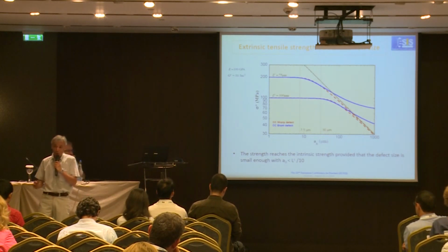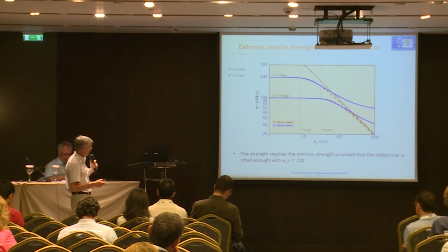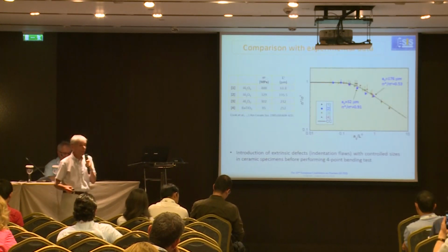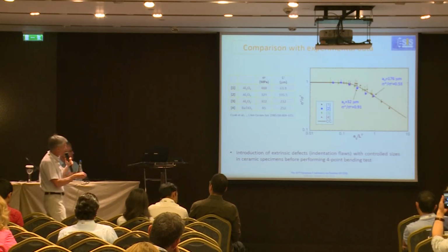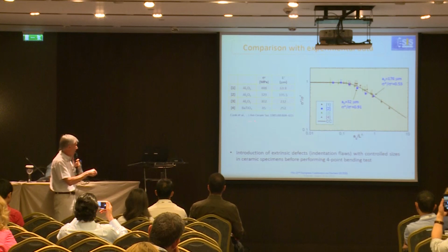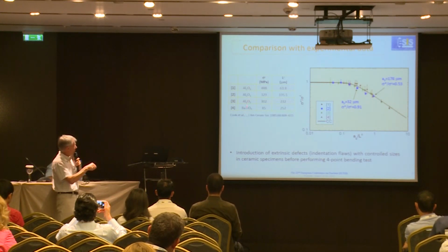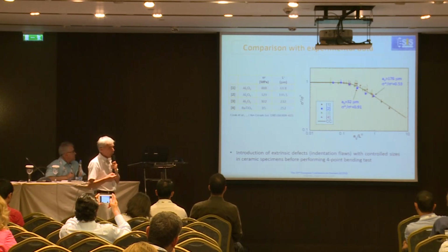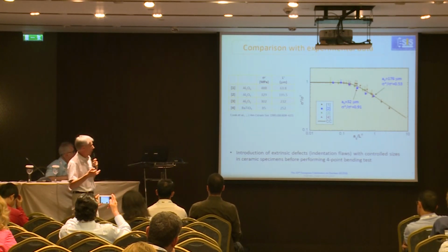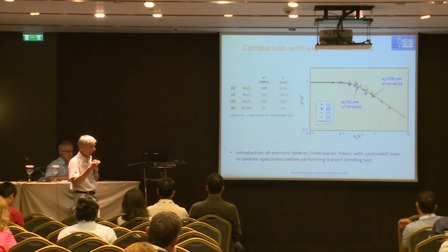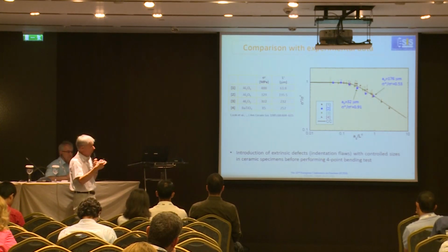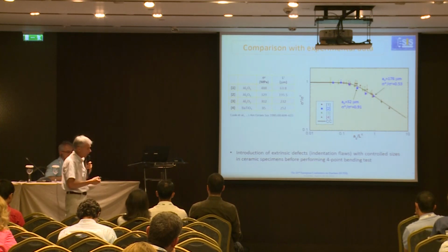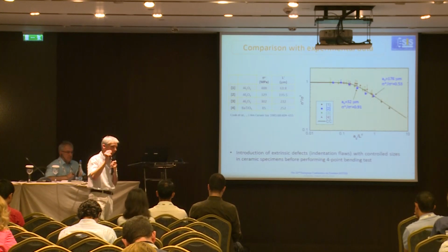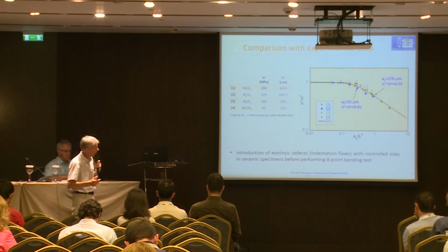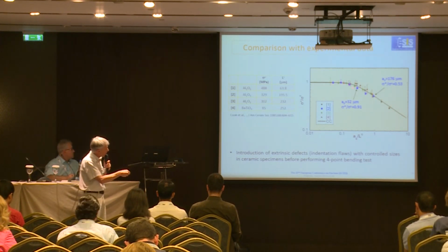Okay, this is only a numerical result, and we would like to compare with experimental data. This is done here using the work of Cook on various ceramic materials. Those authors made a 4-point bending test after introducing small defects with controlled size by an indentation process. So they carefully measured the size of the defect. They were sure that the defect always initiates from the indentation flaw, and then obtained those points here.